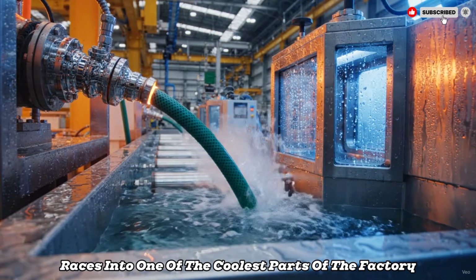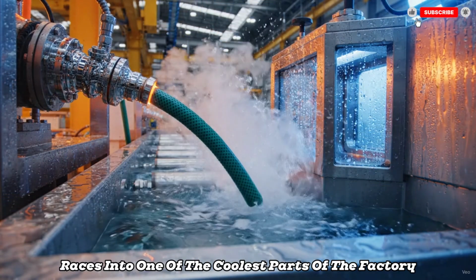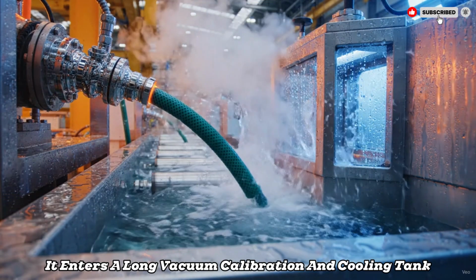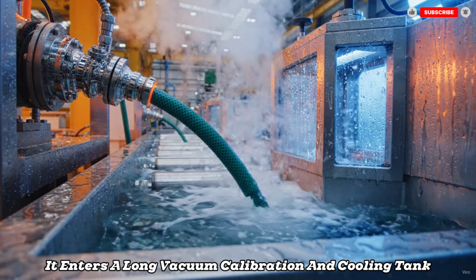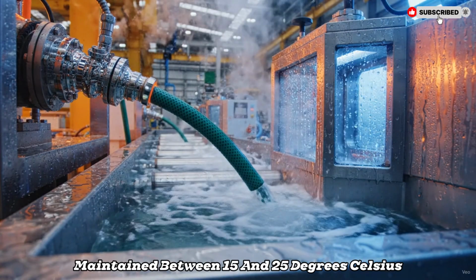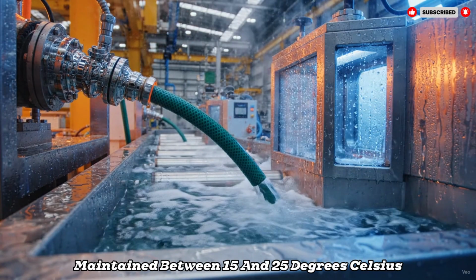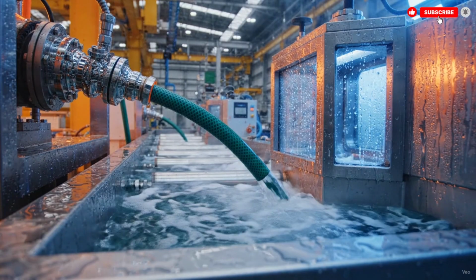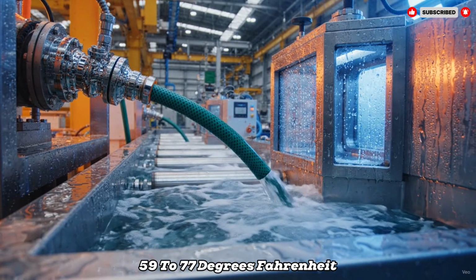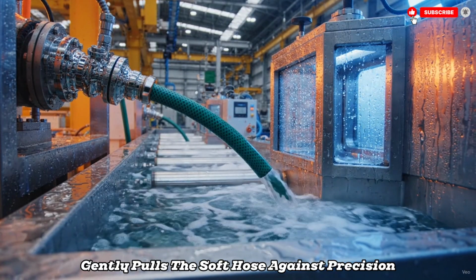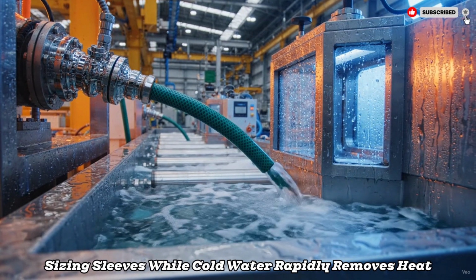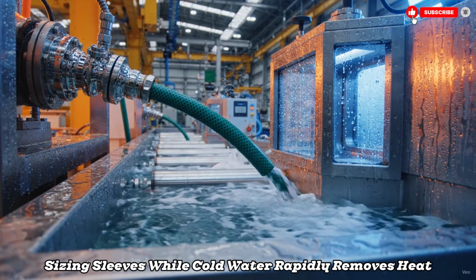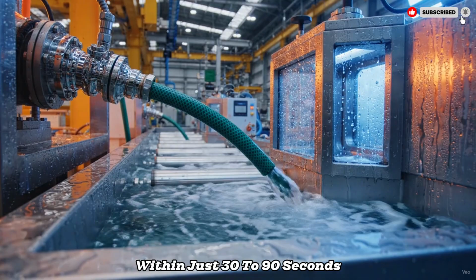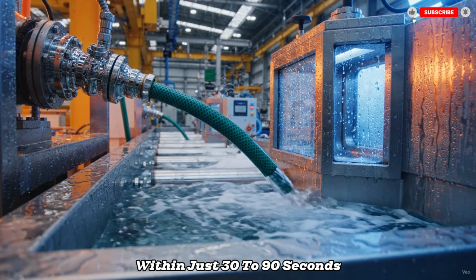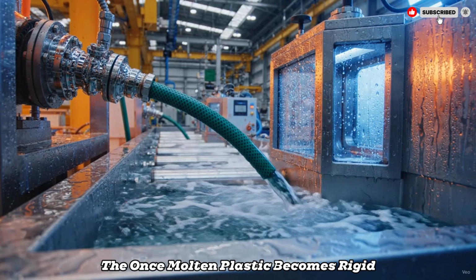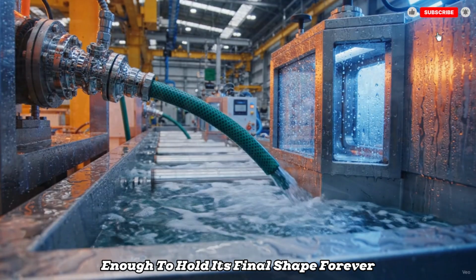Now the hose races into one of the coolest parts of the factory, literally. It enters a long vacuum calibration and cooling tank filled with circulating water maintained between 15 and 25 degrees Celsius, 59 to 77 degrees Fahrenheit. Vacuum pressure gently pulls the soft hose against precision sizing sleeves, while cold water rapidly removes heat. Within just 30 to 90 seconds, the once molten plastic becomes rigid enough to hold its final shape forever.